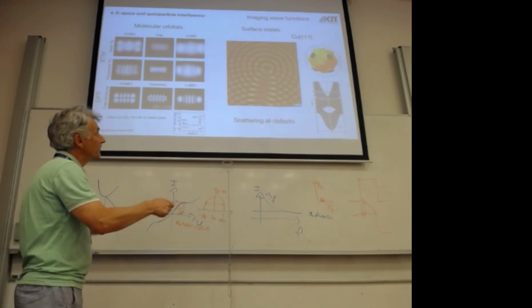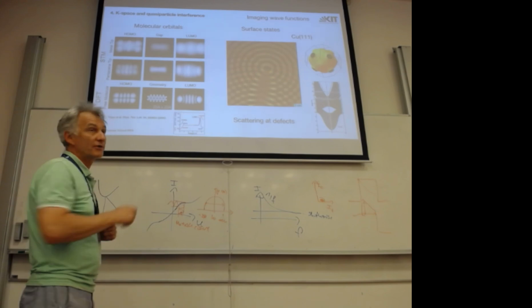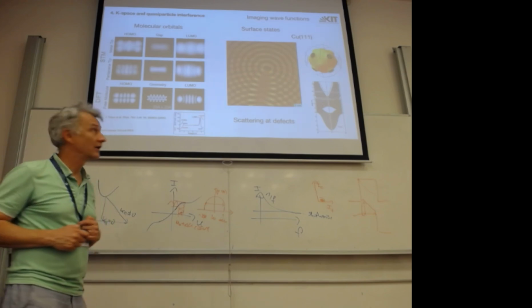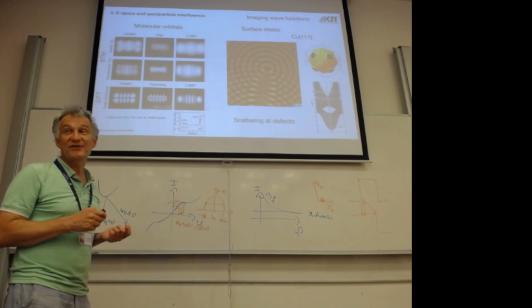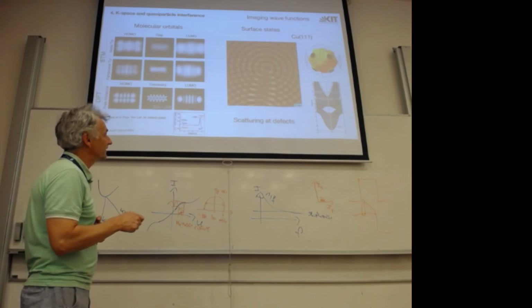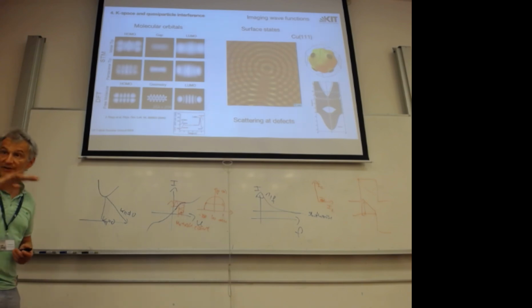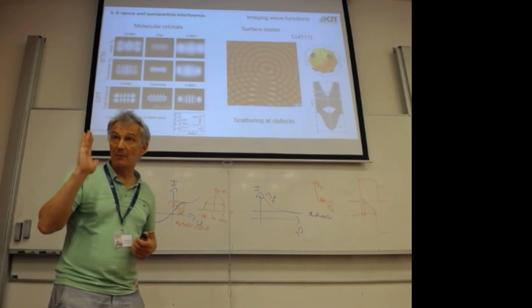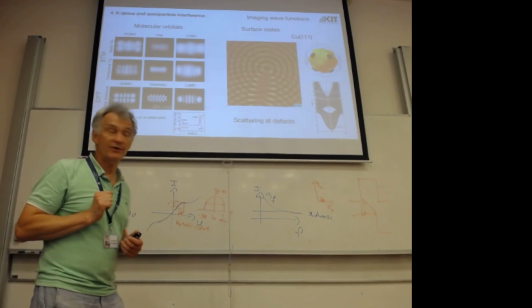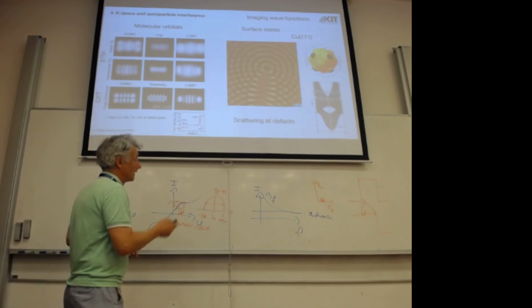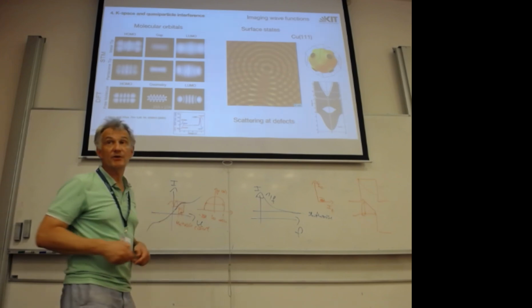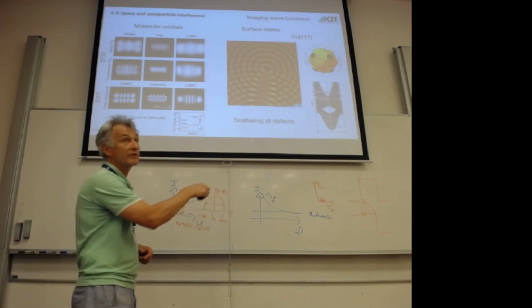And this is such a picture of the two-dimensional electron gas. I plotted the dI/dV as a function of position. And for some reason or another, I have a defect atom here and a defect atom here. Now this two-dimensional electron gas, where I fix the energy by the upper energy of my bias voltage, and I measure the dI/dV, I can see the wave function of this two-dimensional electron gas being scattered from these defects.